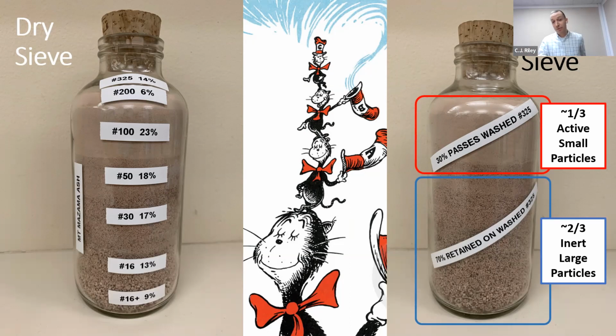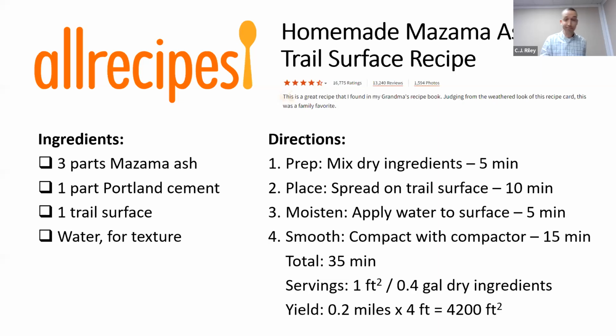You might remember I said we were going to work with a 50-50 ratio of ash to cement. So it's these 1/3 active small particles that we would match in proportion with cement. And that gave us our batch that would give us 3 parts raw ash to 1 part cement. So ultimately, that was our recipe. 3 parts ash, 1 part cement, a trail, and some water. You mix the dry ingredients together so they're interspersed well, spread it on the trail surface, apply water, and move across that surface with a compactor. And that was really our approach for this project after a lot of trial and error with our students.